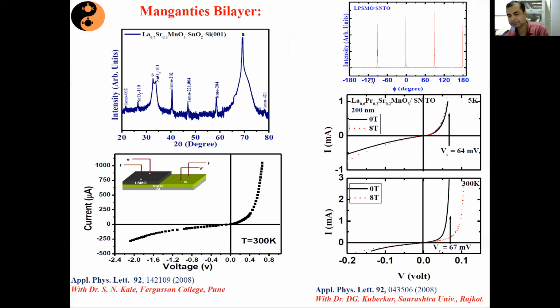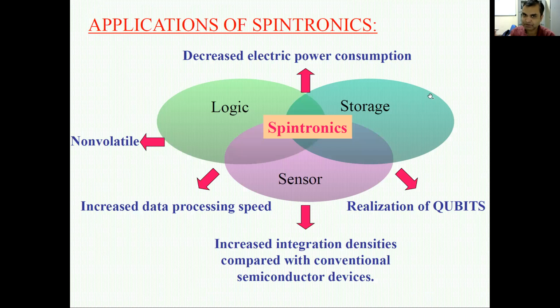This is another example, where we had this magnetic material and integrated it on a semiconducting substrate like niobium doped strontium titanate. If you look at its IV characteristic, it shows non-linear IV. That means it has a rectifying behavior. But the moment you apply a magnetic field, say 8 Tesla, this resistivity completely changes at room temperature. So just by applying a field, you are changing its resistivity. This allows us to control the resistivity by applying a magnetic field, or one can control the magnetic property by applying an electric field. Such devices are spintronic materials.